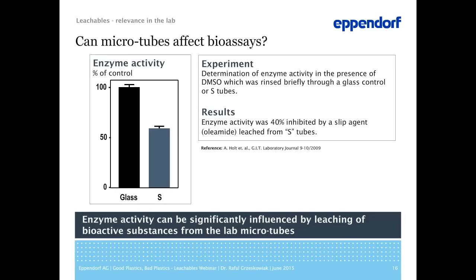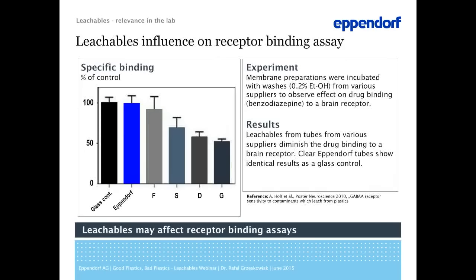This effect, however, was very unstable, and upon closer investigation appeared to be, unfortunately, an effect of the tubes he had in his lab, or more specifically, a slip agent being released into his samples, oleamide. So you might imagine his frustration, and actually this was the very reason he started, as a scientist, seriously investigating leachables and their influence on the bioassays. So the conclusion here is enzyme activity can be significantly influenced by leaching of bioactive substances from the lab microtest tubes. Let's move to the second example.